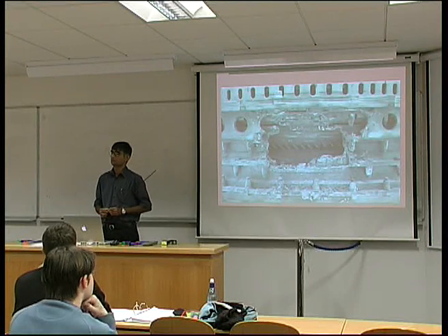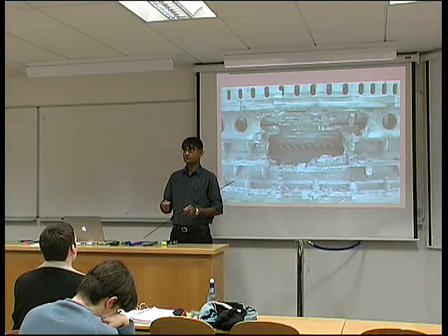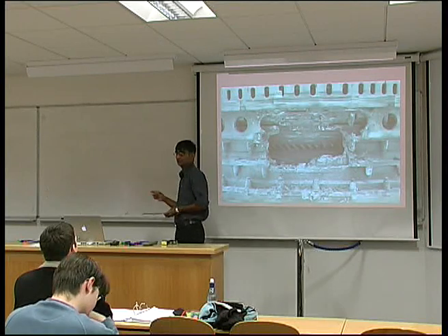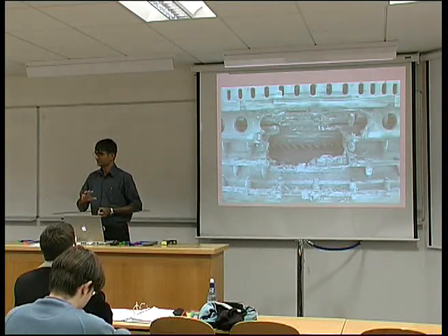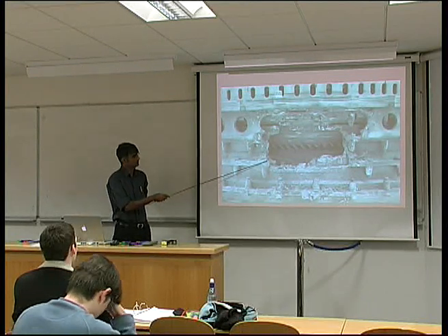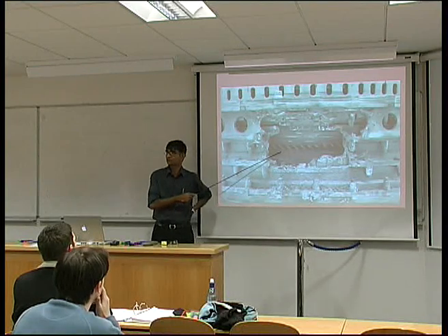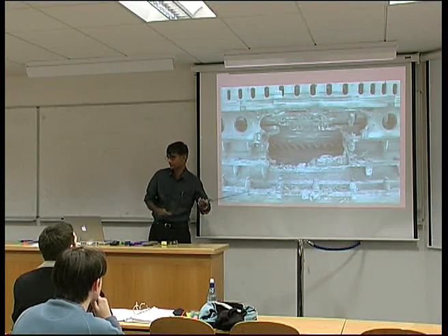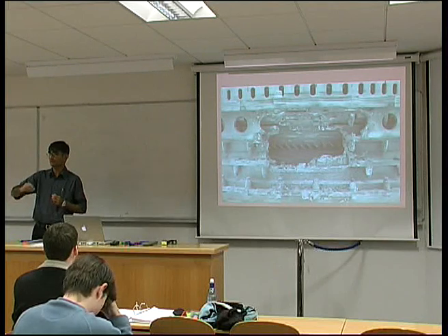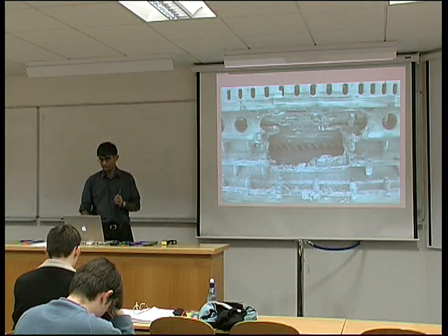It's got a protective oxide film, which is like aluminium. Like aluminium, it has a very large and totally spontaneous enthalpy change when you oxidise it. So once you get the reaction started — and that's the critical thing — it's very hard to stop it. This is a consequence of a titanium fire in an aircraft engine; you can see all these plates have basically disappeared, and this can happen in a very, very short period of time. This is the reason why we don't use titanium beyond about 400 degrees centigrade, because if titanium breaks and rubs against another piece of metal, we will have serious consequences in an aircraft engine.